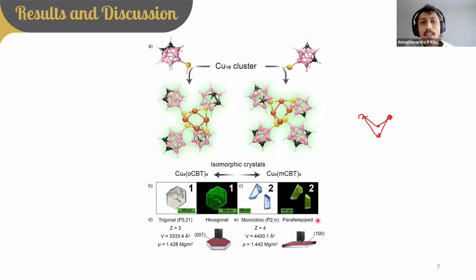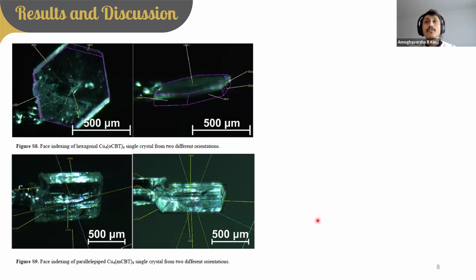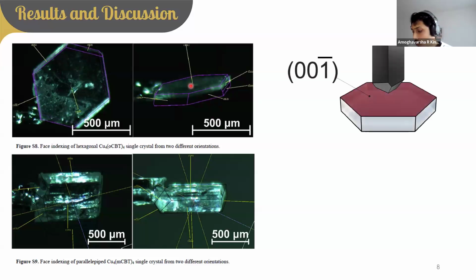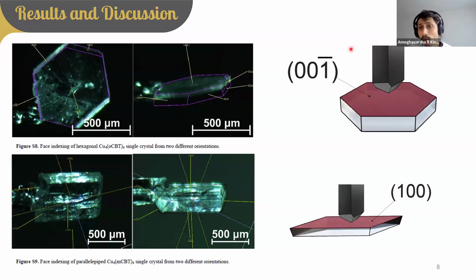After this, we did the phase indexing to understand which phase is available for indentation. For this, we loaded the crystal onto the single crystal X-ray diffractometer and indexed all the phases. We selected the (0, 0, -1) and (1, 0, 0) phases for Cu4 OCBT and (1, 0, 0) for Cu4 MCBT.